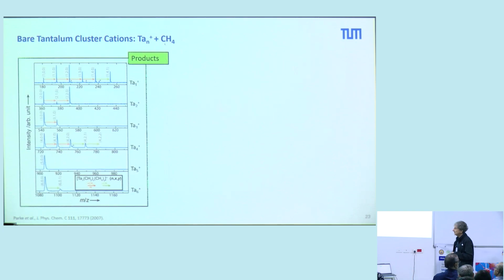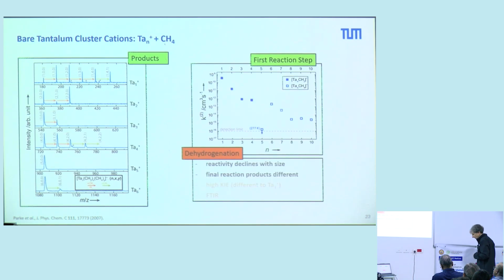Of course, you can do this as a function of size. And you see the tantalum dimer. We have a second CH2, and then nothing happens anymore at these experimental conditions. Tantalum 3, we have 1 CH2. Tantalum 4, again 1, 2, and then we have molecularly adsorbed methane. Then if you go to the 5, it is inert. That means you see this very strong size dependency of the chemical reaction. And we can also measure rate constants of the first step. Here for atom, dimer, trimer, tetramer, and you see that indeed the atom is specific.